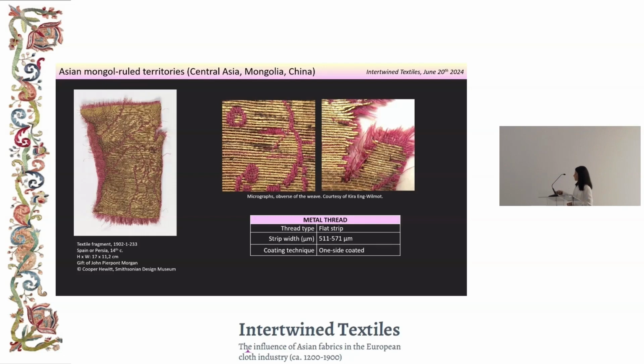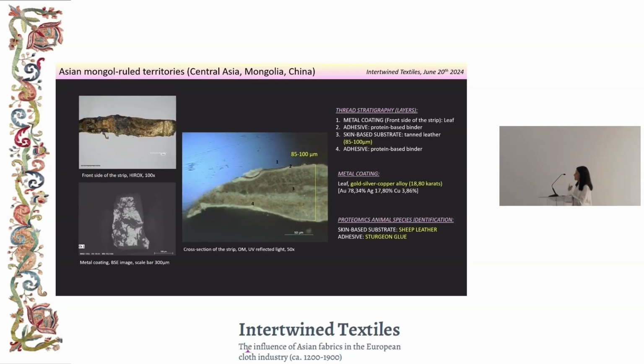In this case, the coating was just on one side, and this is the only difference that we have found with the previous strips. So the coating was not almost pure gold, but was an alloy of gold, silver, and copper. So it may be because it was produced in a different workshop, or maybe it was intentionally done in this way for the visual effect that it has to have at the end.